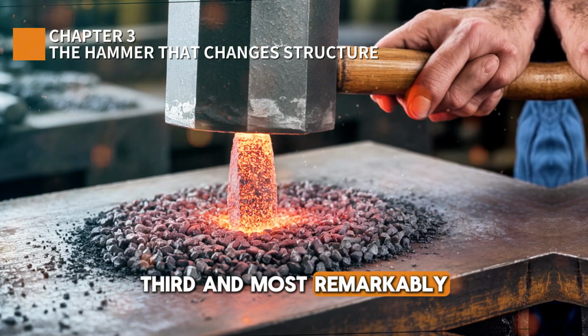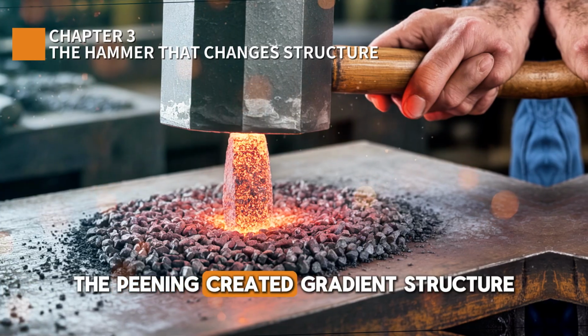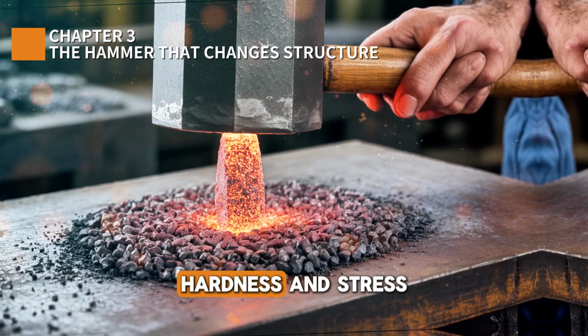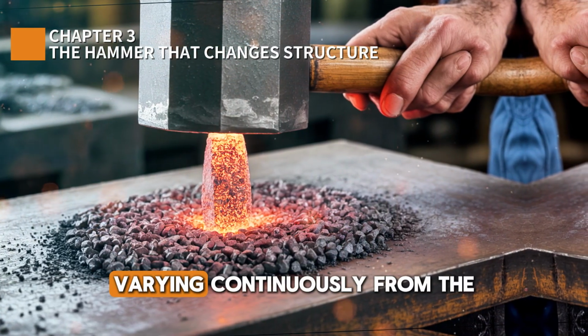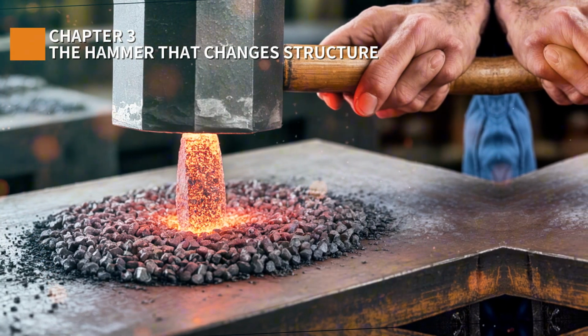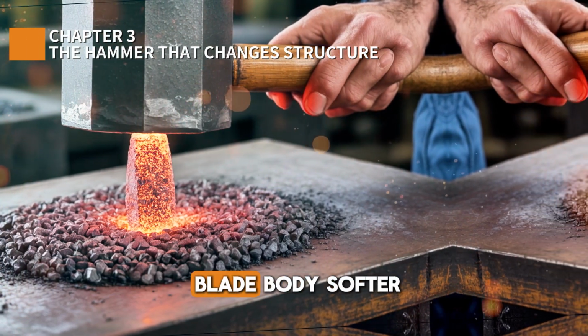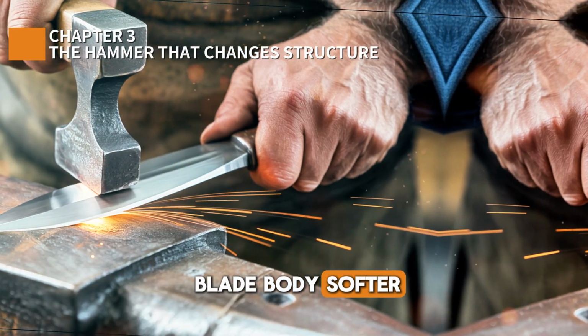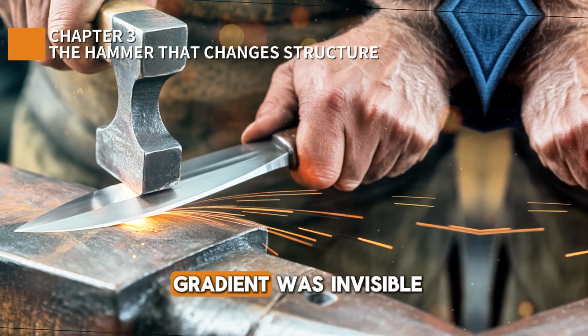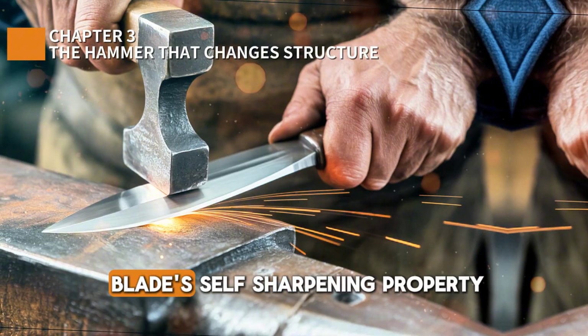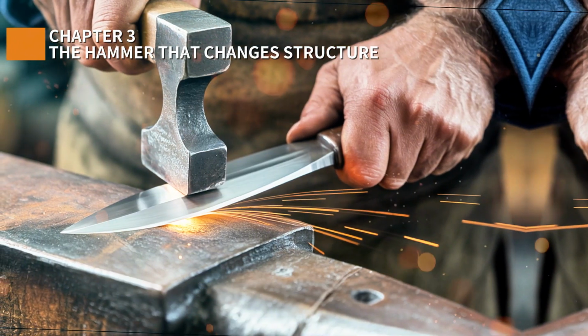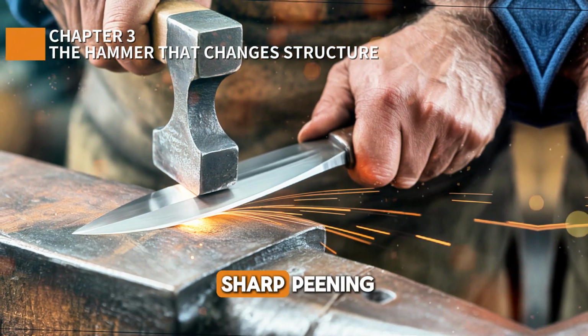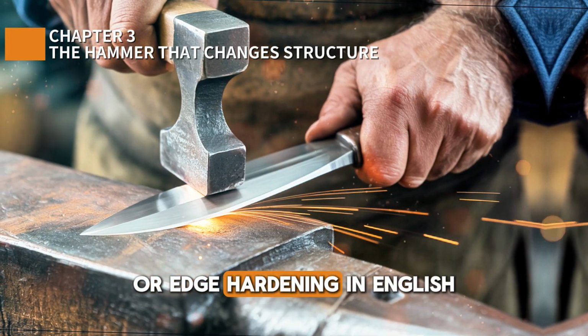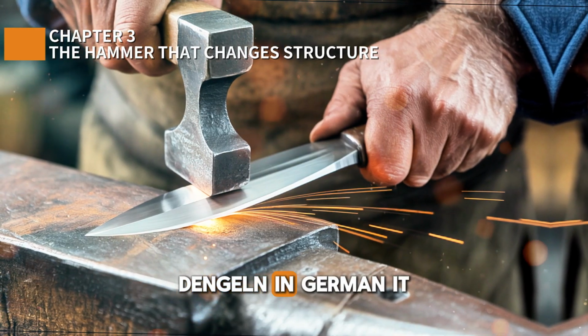Third, and most remarkably, the peening created a gradient structure, hardness and stress varying continuously from the edge apex, maximum hardness, to the blade body, softer, more ductile steel. This gradient was invisible but critical to the blade's self-sharpening property. The technique was called sharp peening, or edge hardening in English, Dengeln in German.